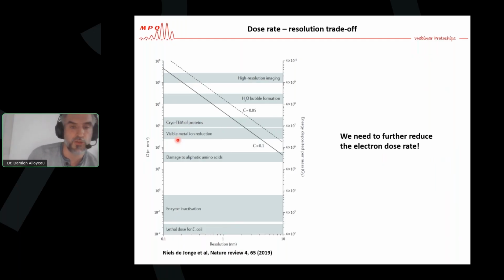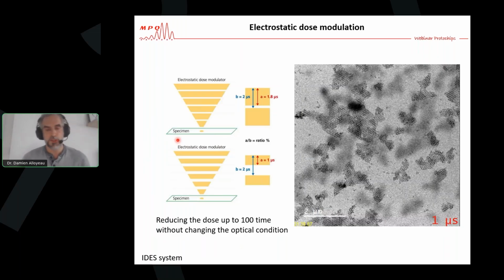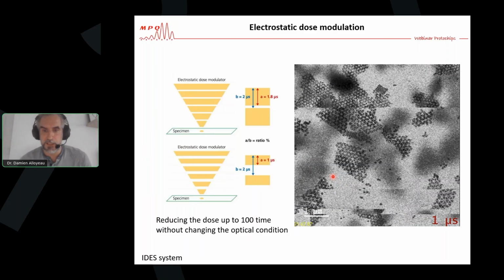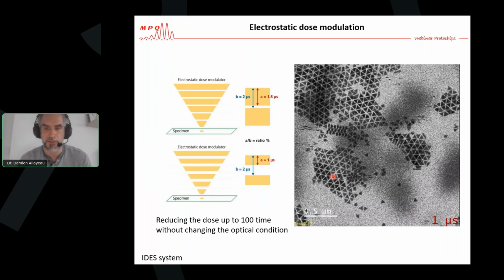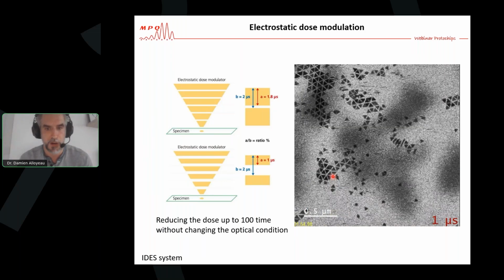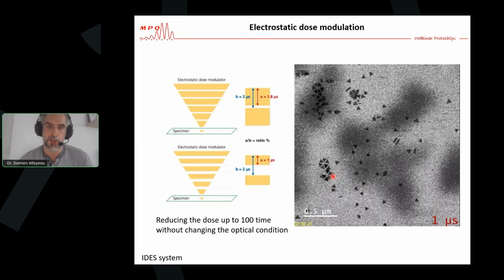And I'd like to show you two new tools that can be used to improve this trade-off. The first one is the use of electrostatic dose modulation. Here I'll show you a study where we work on the stabilization of the structure of supercrystals. And the problem that we had is well exemplified in this video. When you increase the magnification, you increase the dose rate in STEM mode, and you destroy your nanocrystals.